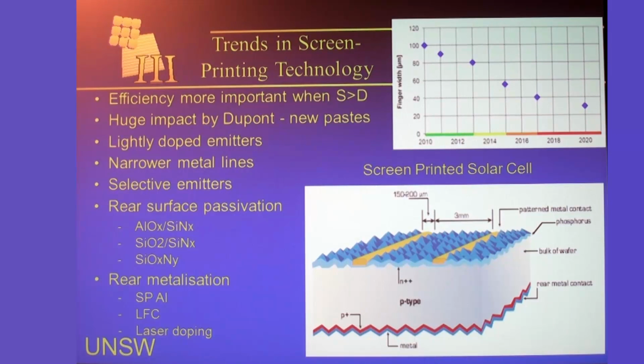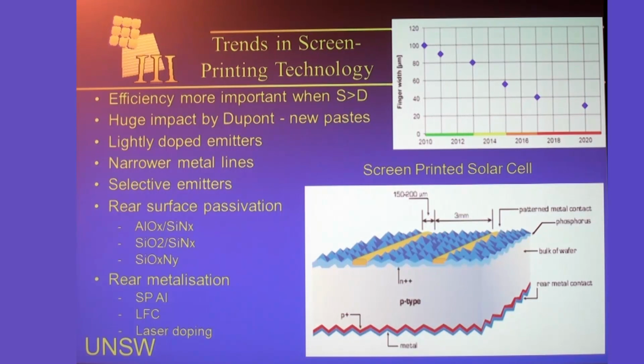The three preferred approaches for passivating the back surface seem to be an aluminium oxide layer capped with silicon nitride. Another one is a thin thermally grown silicon dioxide layer or PECVD deposited silicon dioxide layer, also capped with silicon nitride. And then a third option, being pursued primarily by Centrotherm, is silicon oxynitride as a rear surface passivating layer. So Centrotherm are now offering turnkey systems based on this technology. They're claiming their efficiencies peak at 20%, and they're pretty much guaranteeing an average efficiency of something like 19.5 to 19.6%. So Centrotherm are doing quite well with that for their rear surface passivation.